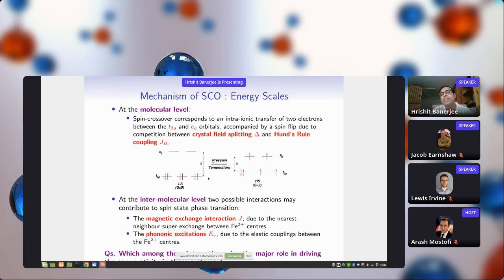So this can be driven by temperature and pressure because the crystal field splitting depends on the bond length between your iron or any transition metal and the nitrogen or oxygen, and how much they overlap, and hence you can drive this easily by changing the bond length and the volume, and this can be driven by temperature or pressure. However, what is very interesting is what happens at the intermolecular level. So when you go to connected systems, when you go to coordination polymers or higher connectivity systems where long-range ordering is possible, what are the two possible interactions?